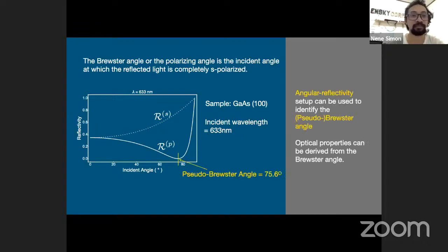So here, I show curves of the angle-dependent reflectivity by a gallium arsenide substrate. The illumination wavelength here is 633. So we can analyze the sample by looking for some features like the minimum of the P reflectivity located at the sample's pseudo-Brewster angle. So the special angle can be used to identify the sample's optical property.